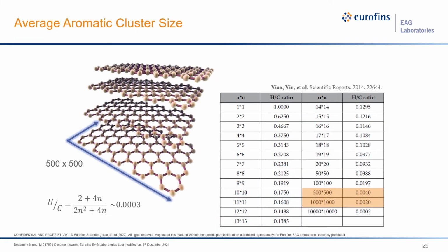Xiao et al. showed that the hydrogen to carbon ratio can be used to predict aromatic cluster sizes by producing biochars using diverse ingredients and systematic processing in their experiments. In this table, they provide a relationship between the dimension of polycyclic aromatic ring and hydrogen to carbon ratio. If we compare our result, the analyzed composite seems to have slightly greater than 500 rows and columns of benzene rings per graphene sheet.